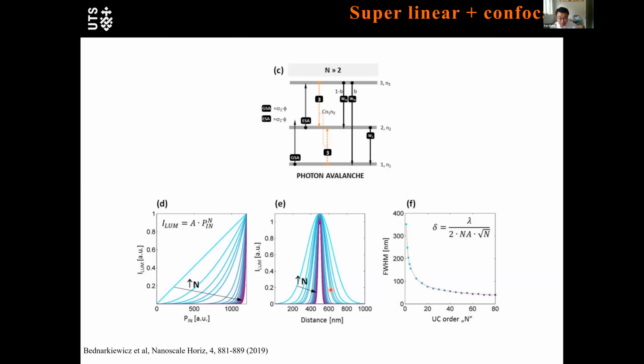So in 2019, Arthur published one theoretical paper describing this. Inside this nanoparticle, we have really interesting energy looping. I won't go through the process here because of limited time. But generally, you can think some of the photons will be reused in an energy transfer cycle, and then your photon effect can go to more than 10 or close to 20. With that, if you match certain wavelengths and select a certain range of the power-dependent curve, like in this figure, your power dependence can be really sharp. Using this, by selecting a certain range and directly scanning, you can have really high resolution.